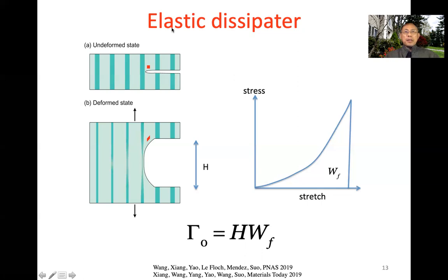Now, this mechanism is an elastic dissipator, because before you have any fracture, the fiber is an elastomer, and the matrix is also an elastomer. Both materials are elastic. There's no plasticity, no hysteresis. So you can cycle many cycles without fatigue. However, when it breaks, you dissipate an enormous amount of energy, giving you high toughness, and by this mechanism also giving you a high fatigue threshold. So this is our hypothesis.